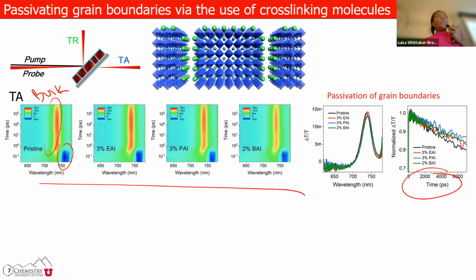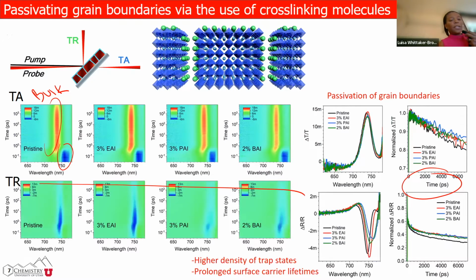Then we translate that into a lifetime, okay? And what we see here is that there's an increase in the lifetime when we put the alkyl ammonium cations in there, okay? And that is an indication that we are passivating grain boundaries within the bulk of the material, okay? So then we change the arrangement of our setup to do transient reflection.